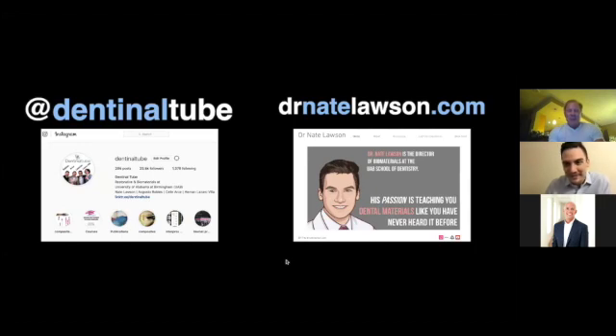Do you mind if I give you my thoughts on that? Yeah, absolutely. All right. So in the lab, the typical default for die spacer is about 50 microns, assuming it's a milled restoration, so 50 to 55. Now you can change that. Someone said their crowns are coming back too loose. Call the lab and see what the default is. They're also going to increase the die spacer if it's an onlay or an inlay onlay crown where there are internal features, because those will get so tight you won't be able to seat it. So let's say an average of 50.